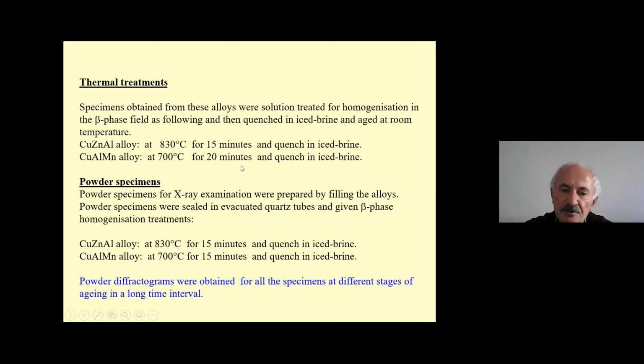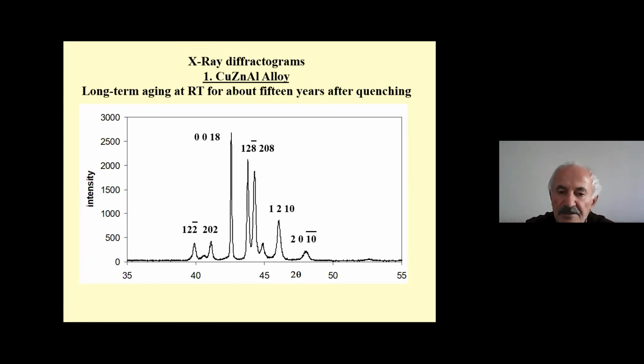Powder specimens for X-ray examinations were prepared by filing these alloys, and these specimens were sealed in evacuated quartz tubes and given beta phase homogenization treatment to release the strain effect and order effect. These temperatures are also the same, and the homogenization time was selected as 15 minutes for both of the alloy samples. Powder diffractograms were obtained for all the specimens at different stages of aging over a long time interval.